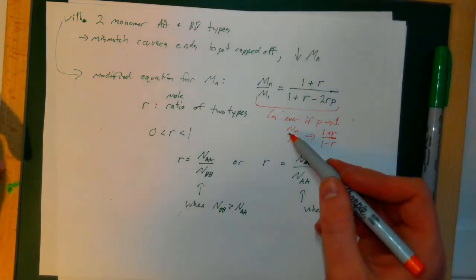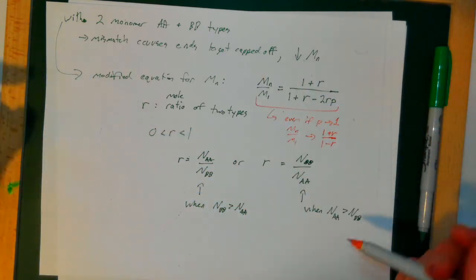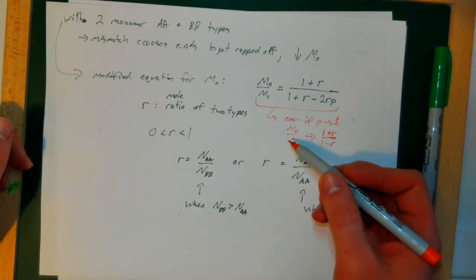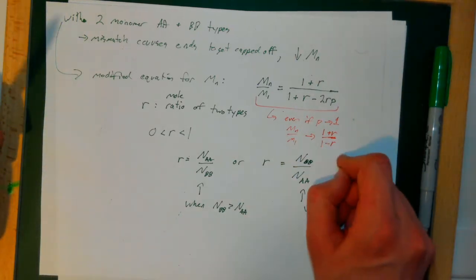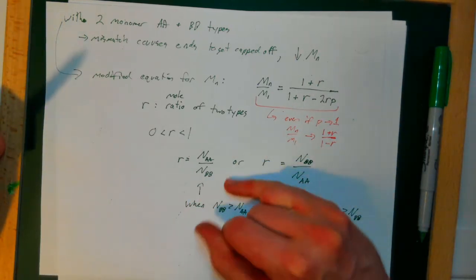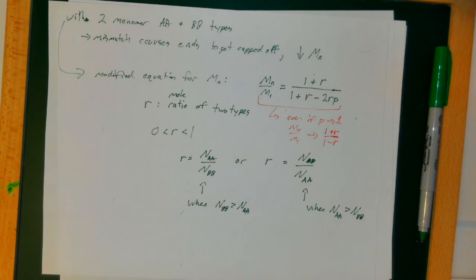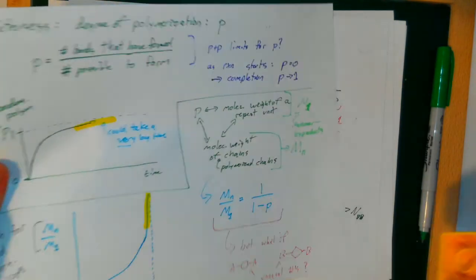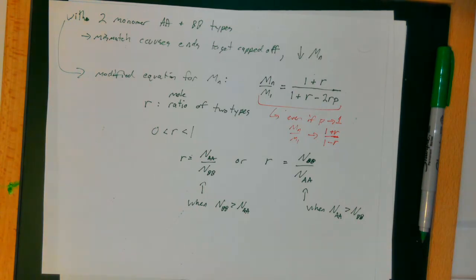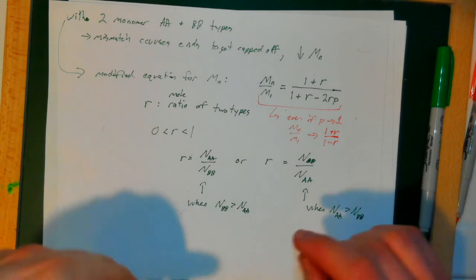So what does this mean? That basically I can allow my reaction to go as complete as possible, and I can limit, if I want to, maybe there might be some applications where I don't want molecular weight super high. I can choose to limit molecular weight either by controlling the mole ratio of these two things, or by controlling the time that I allow polymerization to occur. So it's my choice, right? For some applications, it might be easier to limit molecular weight one way or the other.